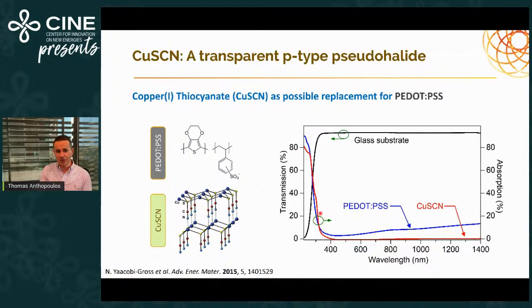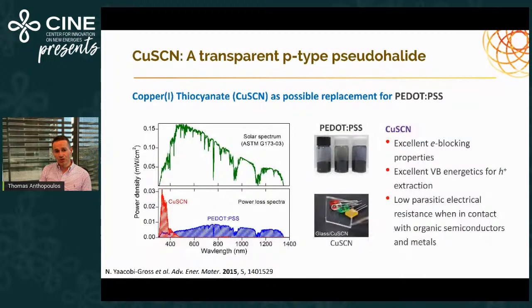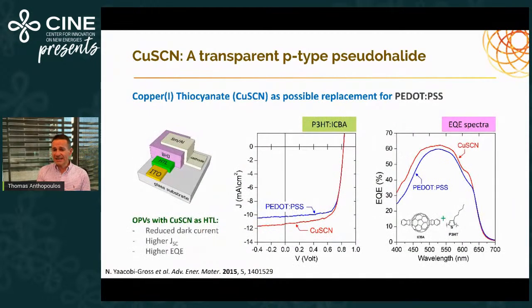And as you can see here, this is a transmission through the film. You see the PEDOT:PSS is particularly bad when it comes to the near infrared part of the electromagnetic spectrum. We see there is a lot of absorption, which essentially leads to power loss. So if we compare copper thiocyanate as an HTL layer and PEDOT:PSS as an HTL layer, by replacing PEDOT:PSS with copper thiocyanate, we can actually gain back all this power loss, which is easily a few percent at least from a device. So this is exactly what we've done.